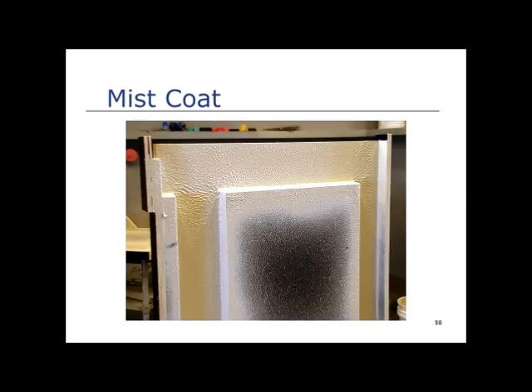So your mist coat, here's a mold that was sprayed. You can kind of see the texture and the overall degree. Spraying is a very fast way of applying it. Again, it's only about a 1/16 of an inch thick, and the key to remember is we've just sprayed a very thin layer of concrete into a mold, and now 2 things are going to happen to it. One is it's going to start setting up and firming up, but that happens relatively slowly. The thing we're battling is it's going to dry out, and that's the last thing we want to have happen. We don't want this thing to dry out on us. So once you spray your mist coat, you better start applying your backer right away.